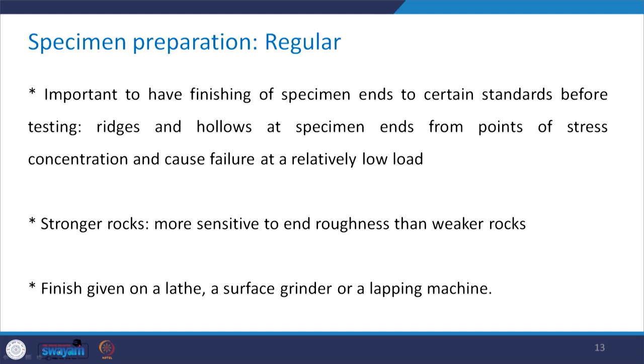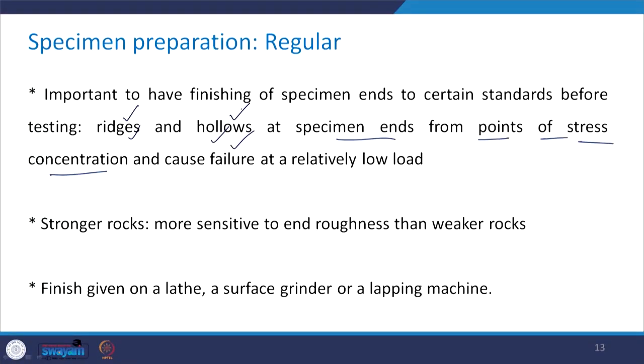Once we obtain this, the ends of the specimen may not have that particular finish. So, it is extremely important to finish the specimen ends to certain standards before we test. The reason being that ridges and hollows at the specimen ends form points of stress concentration and cause failure at relatively low load. Basically, say its strength is much higher, but because of the presence of these ridges and hollows, the strength may come out to be very low in the lab. Stronger rocks are more sensitive to end roughness as compared to weaker rocks. So, finish is to be given on a lathe machine or a surface grinder or a lapping machine.